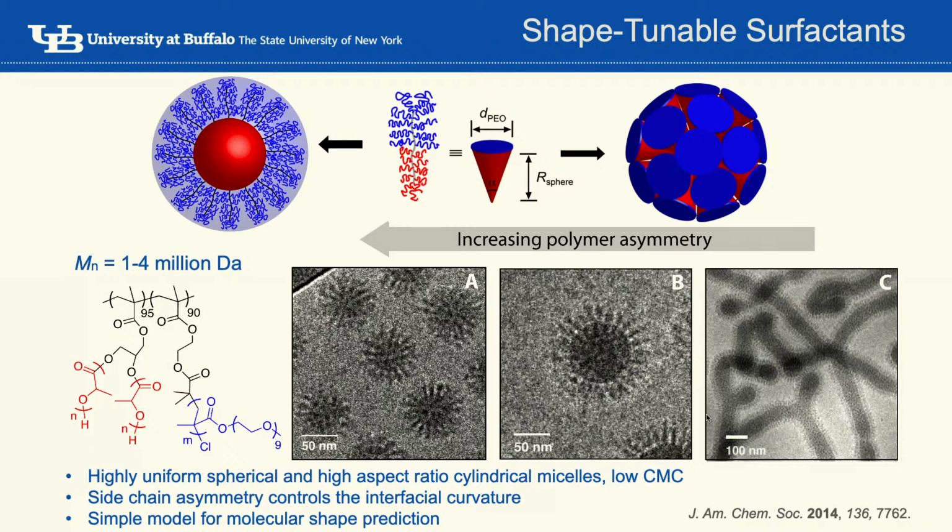These are cryo-TEM images of micelles formed from bottle brush copolymers, and you can appreciate the rigidity of these bottle brushes. This is a hydrophobic core that's shielded with hydrophilic parts of the bottle brushes sticking out of the core. If you measure the length of these hydrophilic brushes, it indicates that the side chain is almost fully stretched out, because we know how many repeat units there are, and we know at full stretch how long that should be, and they correspond to each other pretty well.